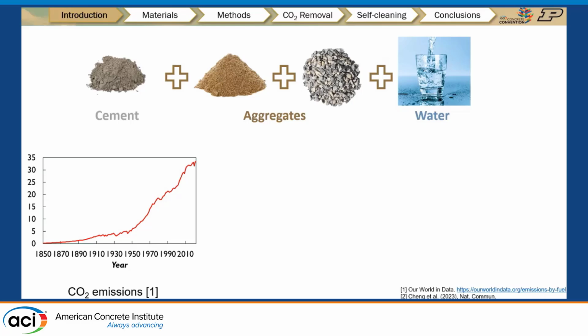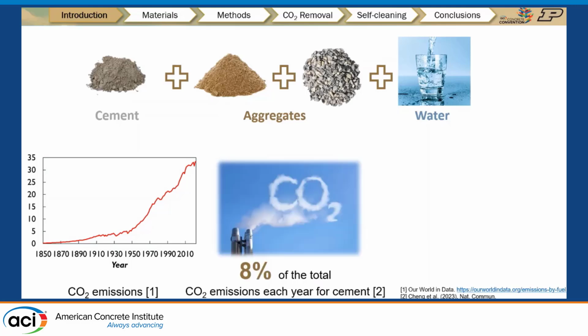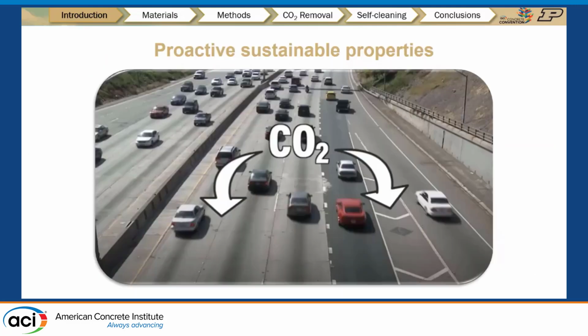So we have known that the carbon dioxide emission has been increasing for the past centuries, and if we look back into our concrete recipe, we found that the production of the cement only contributed around 8% of the total carbon dioxide emission annually. And if we account for the production of aggregates, we're looking at a much higher value. So how can we mitigate this?